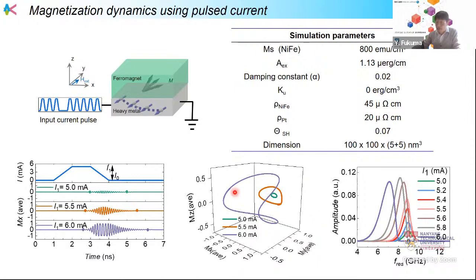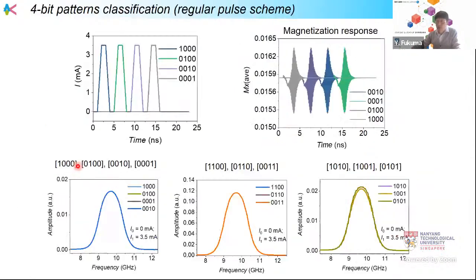So by using this kind of pulse scheme, we try to do the 4-bit pattern classification. For example, when we apply this kind of pulse, the input is 1, 0, 0, 0, for example in the case of the green. Then we can see the precession only in this region. Then in the case of 0, 1, 0, 0, it means that we put the second pulse on, then off. Then we can get this kind of dynamics.